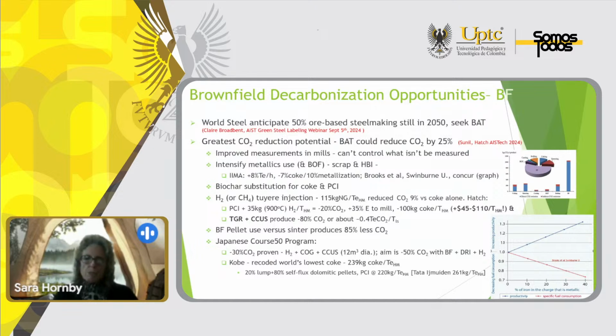Also, Hatch has run some calculations, and they believe that post-combustion PCI, this pulverized coal injection, plus 35 kilograms of 900 degrees centigrade hydrogen would reduce the CO2 20%, increase the energy to the mill by 35%, and would reduce the coke by 100 kilograms. But it would cost a lot, so you need to be careful. But if you add top gas recycling and CCUS to the top of the blast furnace, you can produce an 80% reduction in CO2, which would bring it down to about 0.4 tons of CO2 per ton of liquid steel, which is almost as low as the EAF.